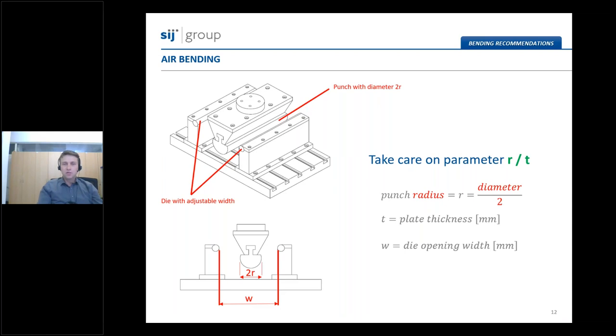So first, we will check the air bending procedure. Air bending is, I think, the most widely used process for bending. In this case, we do not have any special tools. Just one punch with a removable and changeable punch radius that can be used on different types of hydraulic presses. And what we also need are adjustable supports, which should be made of really hard material, harder than the plates that we want to bend. And during this process, the material, which is in the form of a steel plate, is plastically deformed by pushing the plate with the force of the punch into the supports.